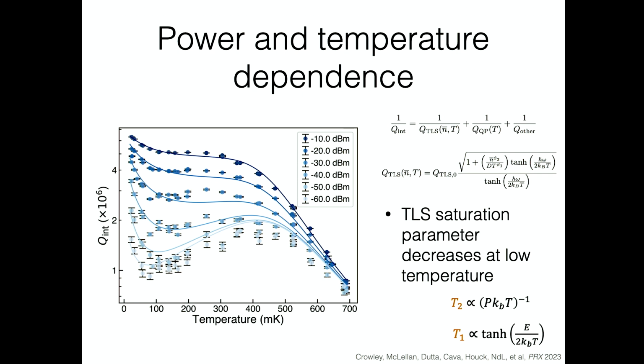Okay, and then we did something that for some reason people weren't doing in the community, but is a very powerful approach for really understanding microscopically where the losses are coming from, which is that we took these power dependence curves and then we just changed the temperature and took a power dependence curve at many different temperatures. And the idea is that you get this whole family of curves, and there's a lot of wiggles and wobbles here.